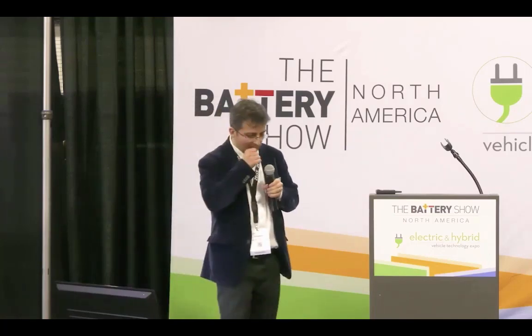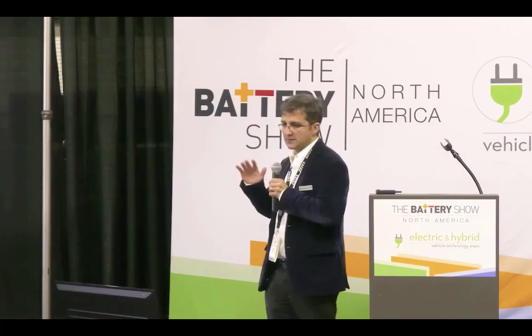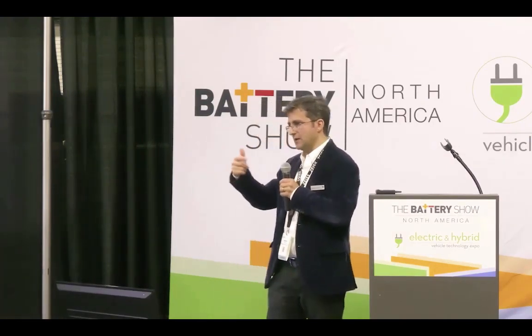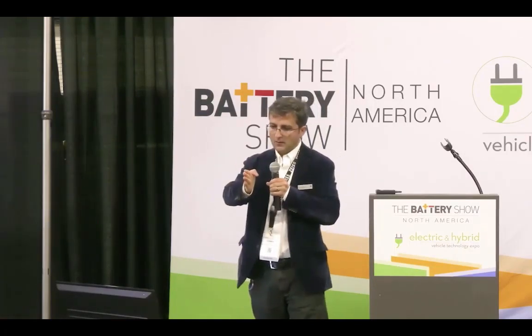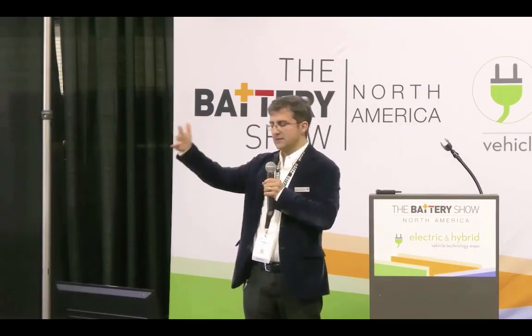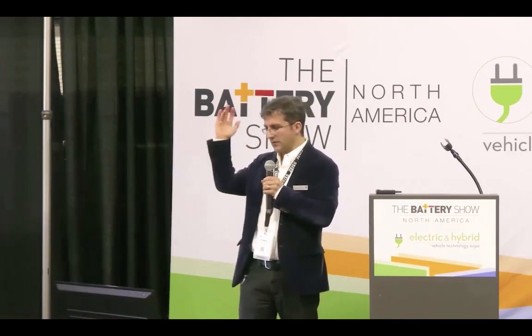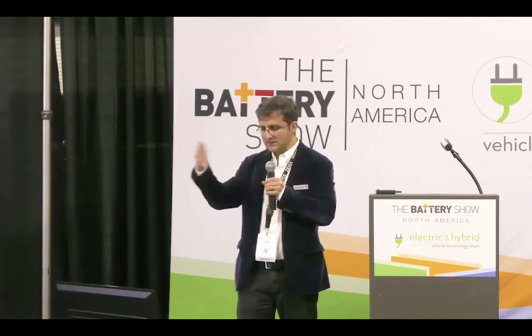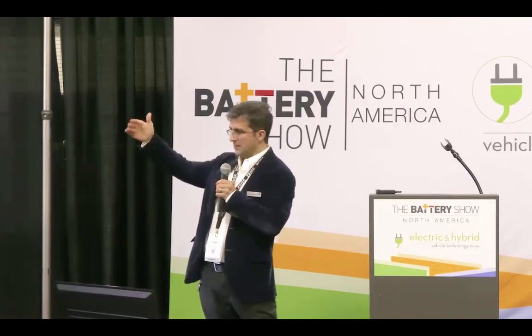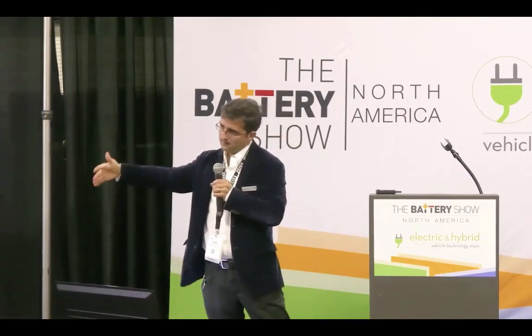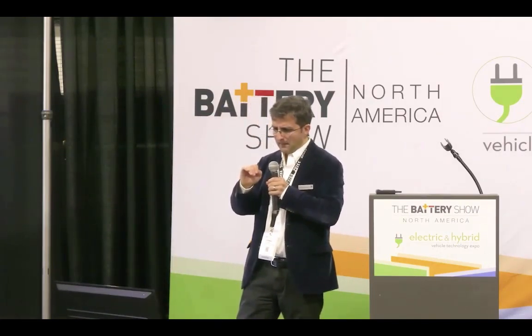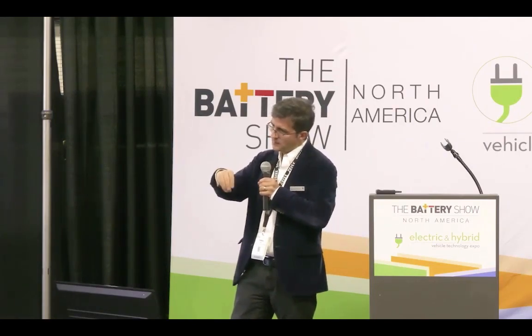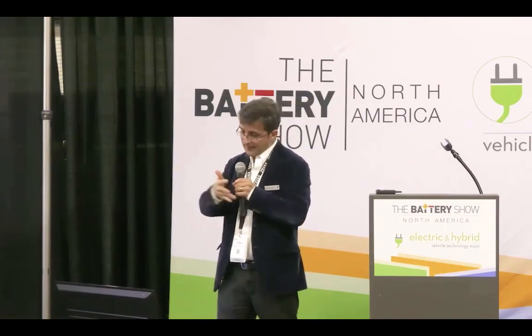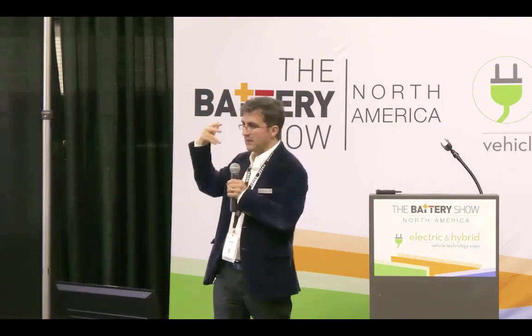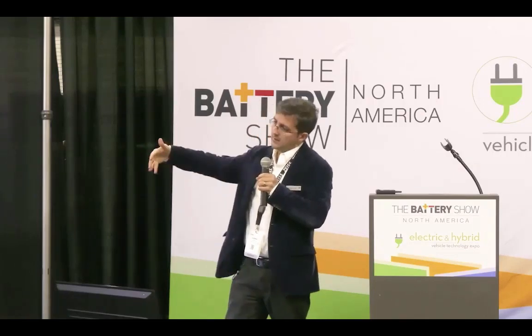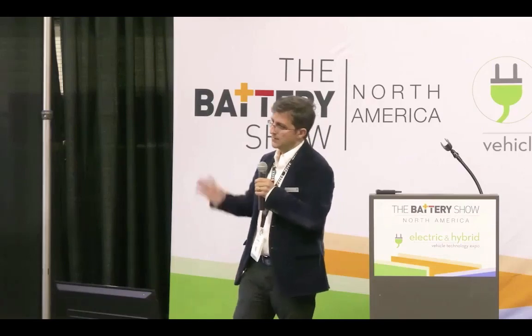Yeah. What I have seen is that the battery manufacturers put the battery through these cycling periods, and they scan the sample when it is fresh, and then they scan it at certain cycles. So let's say they create a battery that goes 500 cycles. They create the battery and then they discharge it, let's say 20 cycles, 40 cycles, 80 cycles, and they can see how the battery is changing over the cycling time. That gives them an idea of how the internal composition of the anode or the electrodes is degrading. I'm not a battery expert, but they have their own models, and they could predict how long the battery could last and still be used. So that's the main idea.